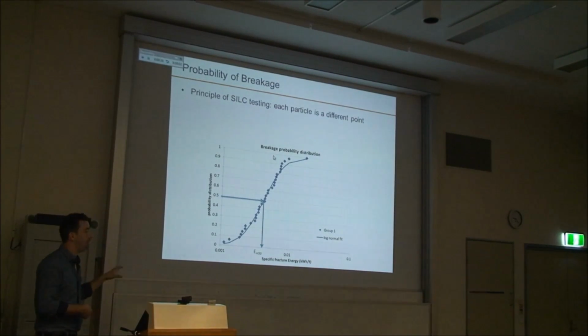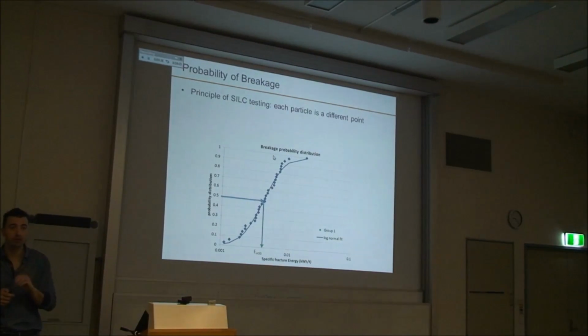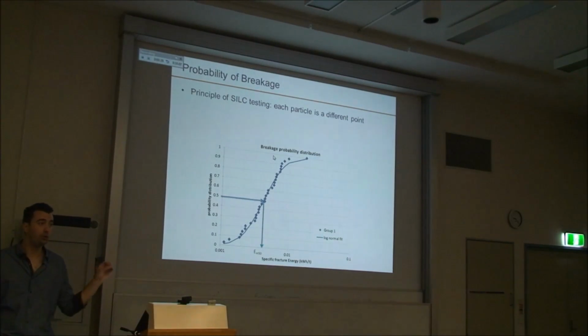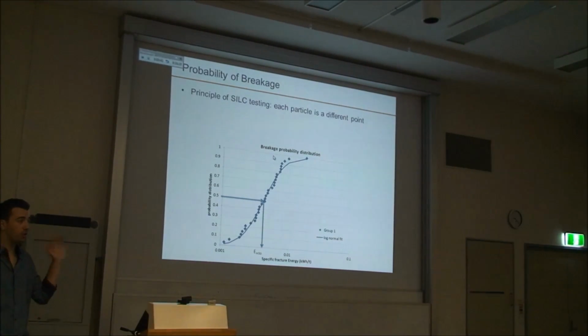So what we can see here is that there is a distribution of strength. There is a distribution of properties within the material. So this is again one sample. I didn't split it, I didn't do anything to it. It's just one sample taken out of copper. There are 2 properties here that can be observed. First is the average fracture energy, which is these points here, and we're going to call it the E50, which is the energy to break 50% of the particles.